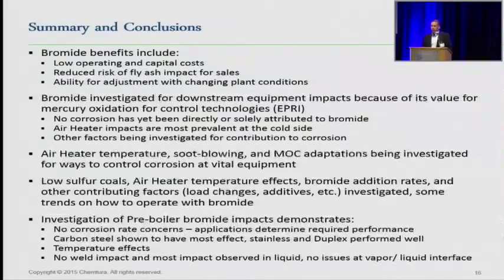And then on our tests of the pre-boiler bromide impacts, we didn't really see a whole lot of corrosion rate issues. I don't really think, for the most part, even in the worst case with the carbon steels, they were overly aggressive for what I would consider reasonable corrosion rates. Again, it depends on how you're using that equipment and what you need to do as far as your maintenance. But the carbon steel had the biggest effect. Stainless steel duplex did very well. And then the temperature effects at higher temperature, we did see a little more, but again, you would expect to see that. I don't think necessarily you're operating at those temperatures all the time. And then really no impact to the welds, except in the liquid immersion.